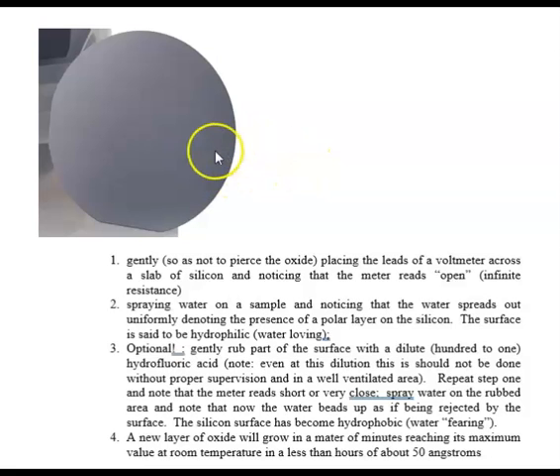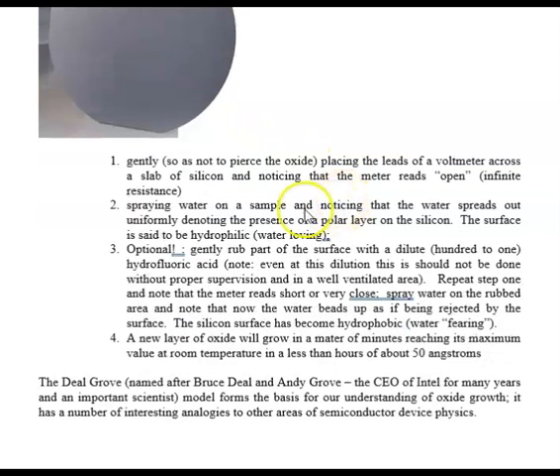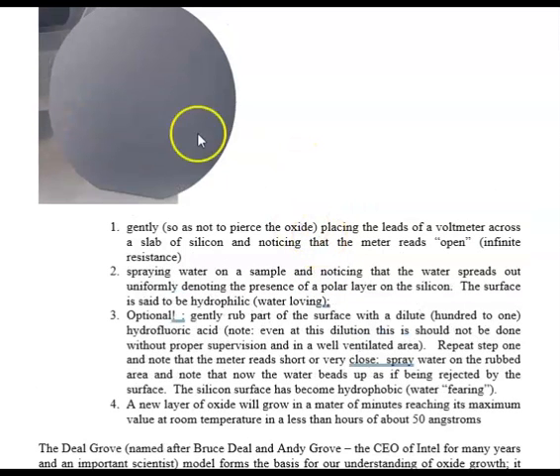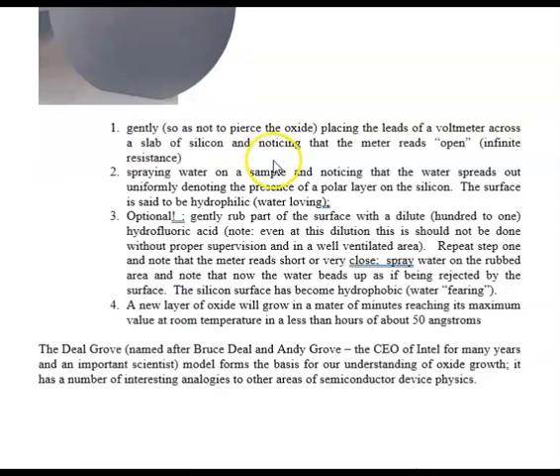And then I leave it sitting on the table someplace, and come back in about half an hour or so, respray the water, and you will notice at that point that the entire wafer becomes, again, hydrophilic, because even in a matter of 10 to 15 to 20 minutes, I get a layer of oxide on the silicon.